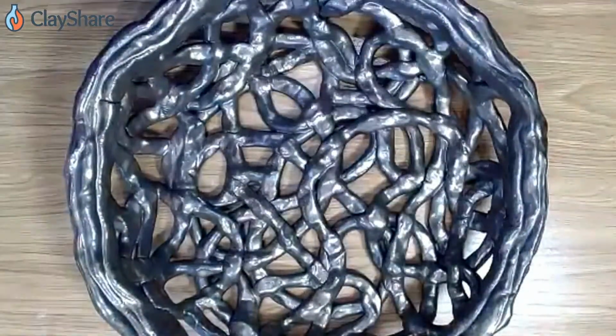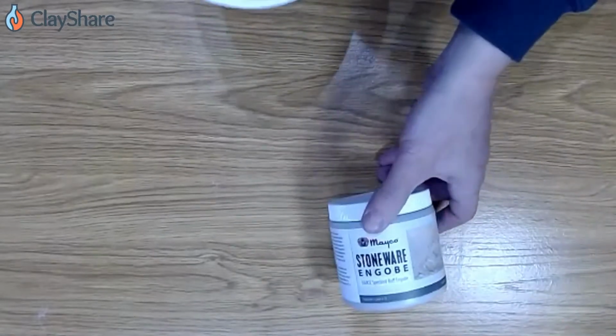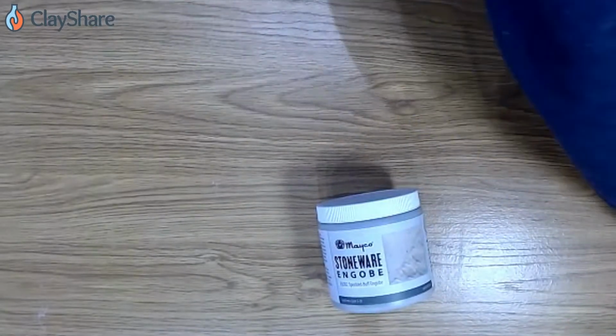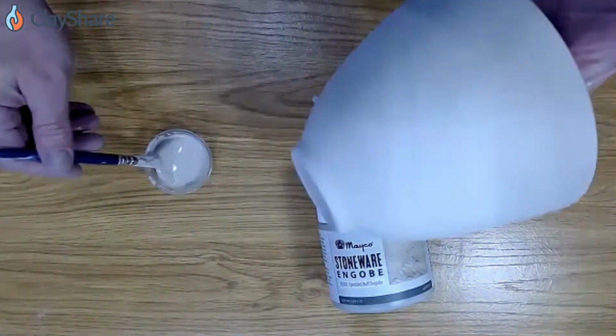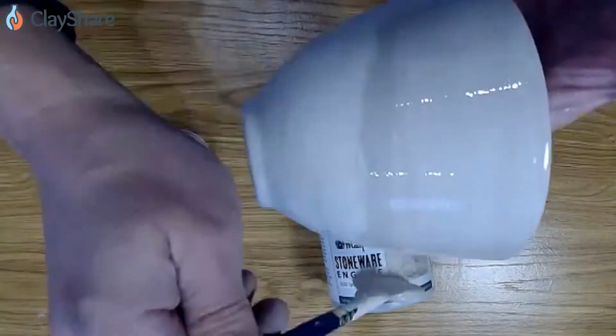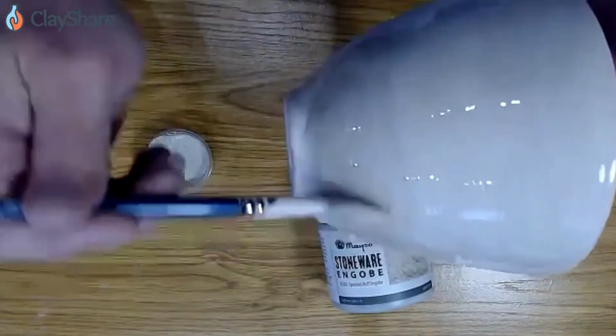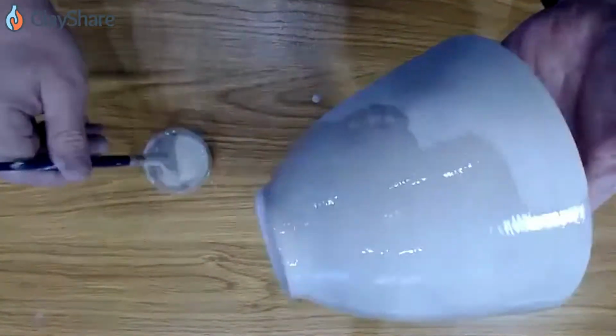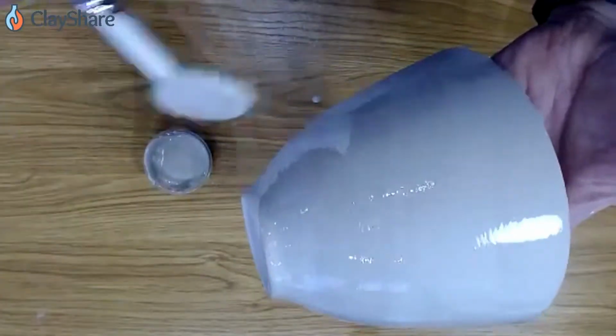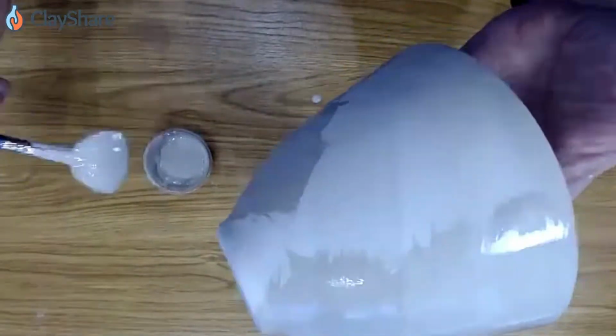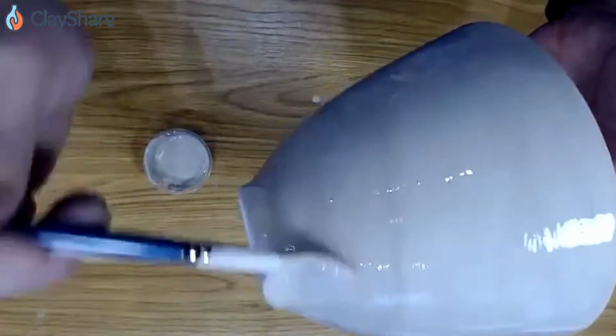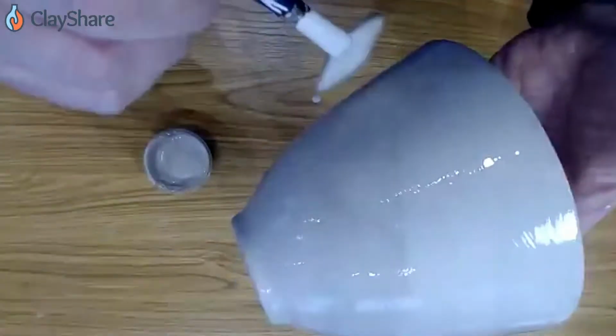The back of this is done with the black engobe. And so we're going to talk about those products. And I'm going to quickly apply another coat of the engobe. So Mayco came out last year with a bunch of engobe colors. And this one happens to be the speckled buff. And so I had applied 2 coats to this bowl earlier today. And I'm going to apply a 3rd coat just to the sides. I'm going to leave the bottom. We find that the engobes generally do not stick to kiln wash if you apply 2 coats to the bottom. If you apply the 3rd coat to the bottom, sometimes with some kiln wash brands, it might stick a little bit. And so the very bottom I'm leaving.